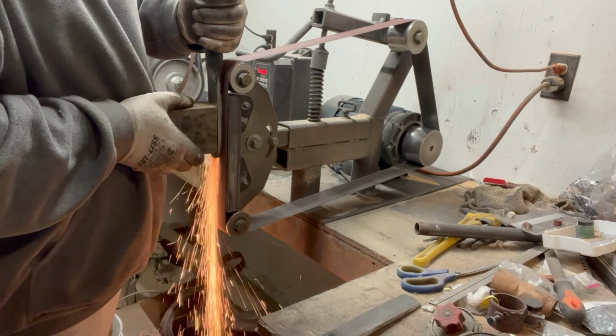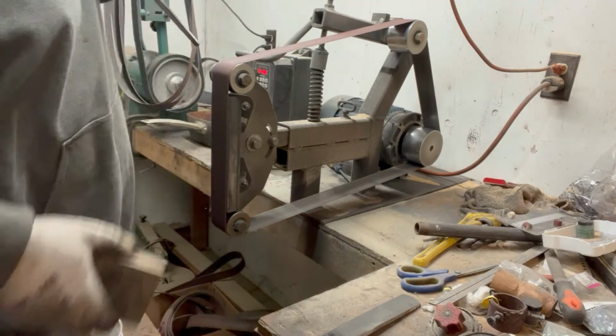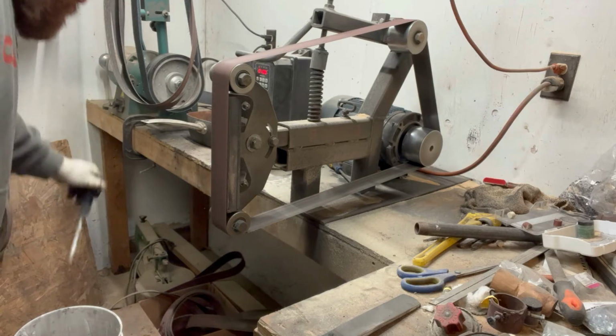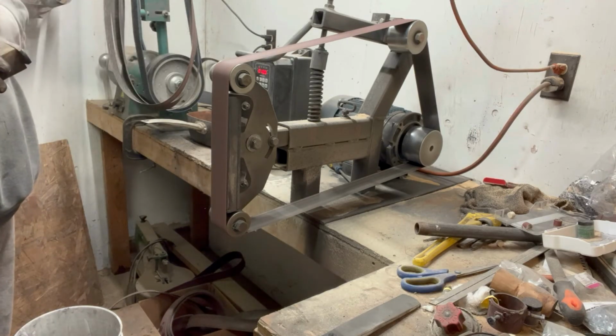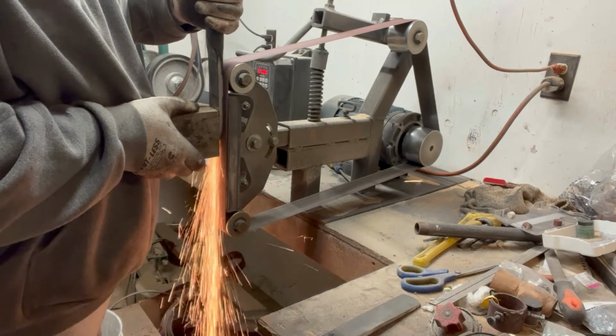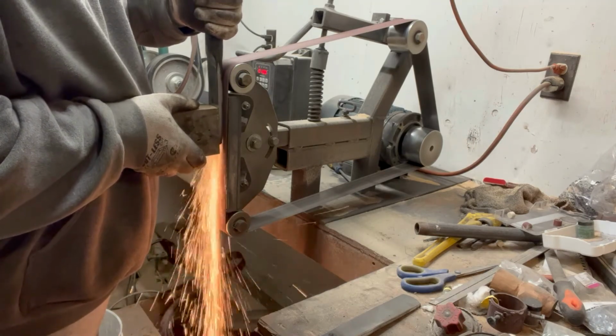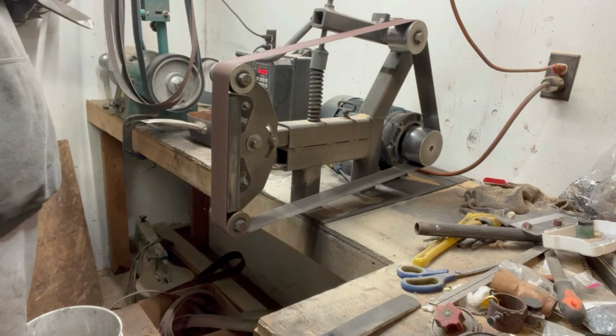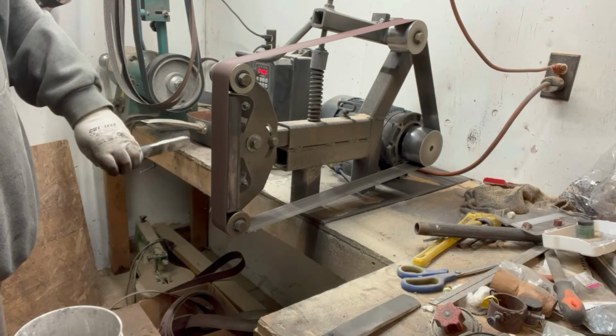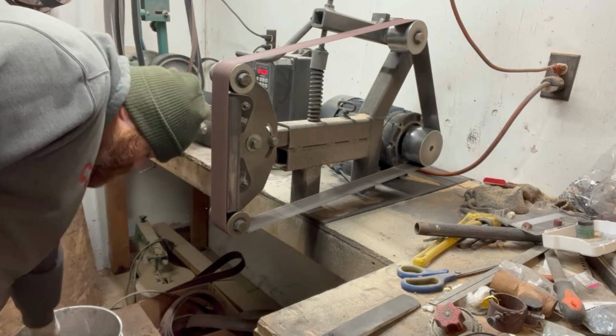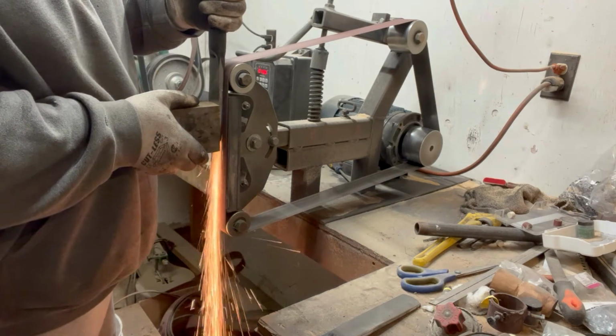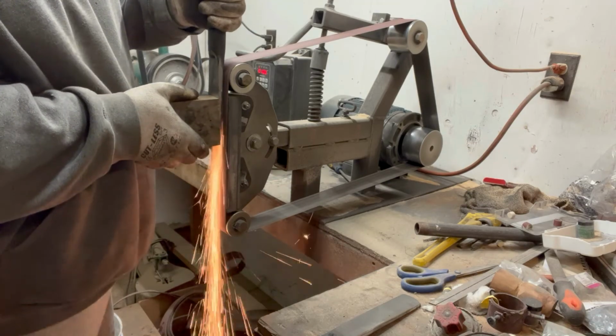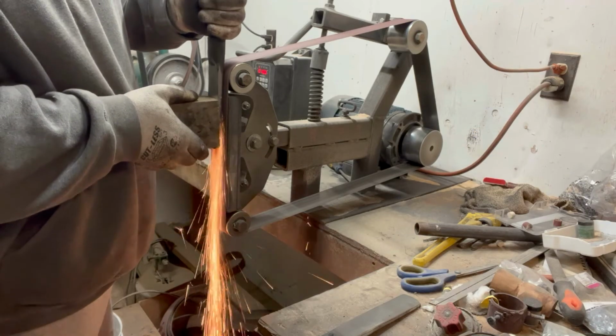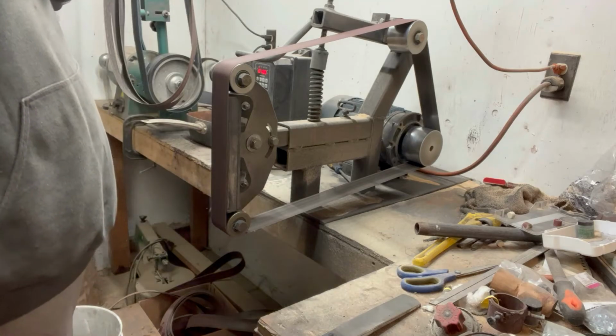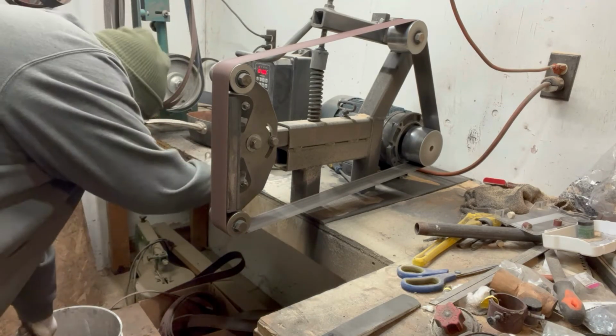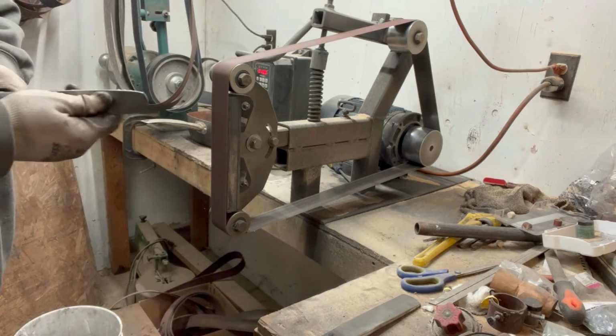Now, I don't care if this thing overheats because we're not grinding hard right now. We're grinding soft. If I was grinding hard, I would. That's another reason why I went to aluminum oxide, is that I'm not grinding hard. A ceramic belt, especially a sharp ceramic belt, doesn't heat your piece like an aluminum oxide would. So if you're not grinding hard, which after quench and temper is done, then use aluminum oxides. They're cheaper for one, they're cheaper for two, and you're not worried about overheating your piece for three because you haven't gone through heat treatment. You've gone through just annealing it. And that bucket down there has water in it.